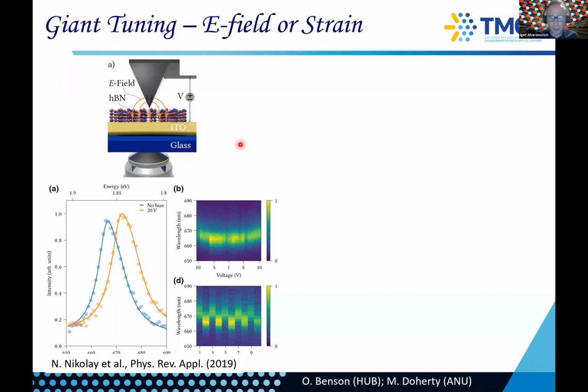So as I mentioned, you can easily transfer it from the copper plate to basically any other substrate. So you can do then electric field modulation. So you can see here that the emission can be tuned by about 10 nanometers or so. Everything is at room temperature. This is just by putting it on ITO, done in collaboration with Oliver Benson.